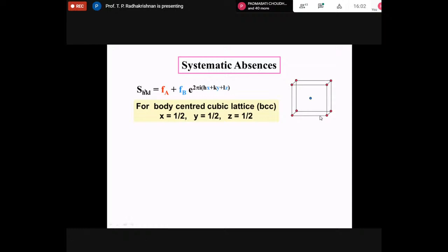So let me write the structure factor for this diatomic basis, a red atom and a blue atom. So red, let us assume, is at origin 0, 0, 0. Blue will be at half, half, half, the coordinate. Why half, half, half? Because it is half along the x-axis, half along the y-axis, half along the z-axis. So this coordinate is half, half, half. It's called actually the fractional coordinate because it determines the fraction of the unit cell length. So 0, 0, 0, half, half, half. So this atom is at Fa into e to the power 2 pi i into 0 plus 0 plus 0. So the exponential will be 1, exponential to the power 0. So it will be simply Fa.